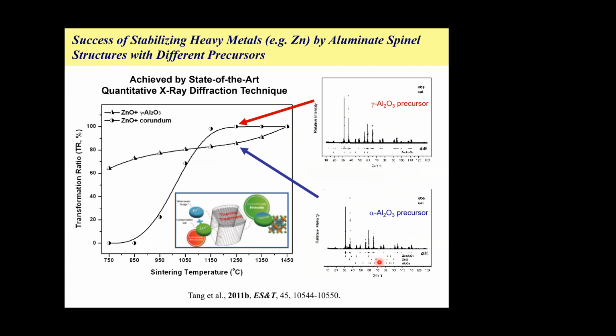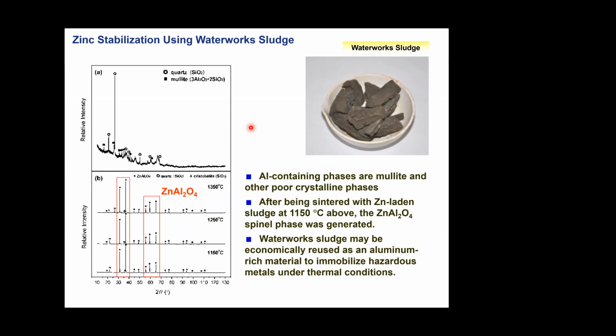We have done this for a lot of different kinds of metal, including zinc, for example. We again find out that at lower temperature, gamma alumina is always more powerful for incorporating metal. At higher temperature, in fact, corundum, which is alpha alumina, is usually more favorable. We try to use all different kinds of compositions that come from the waste stream. For example, wastewater, waterworks sludge, mostly enriched in alumina. We do the same thing. We find the same: the zinc aluminum spinel is the phase that stabilizes the zinc when you're burning this for the new products. And again, there's always a best temperature for you to shoot, not too low, not too high. That is how quantitative analysis can tell us how to control your technique to be just right.